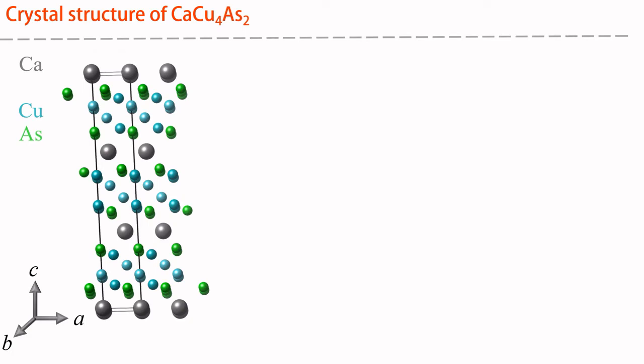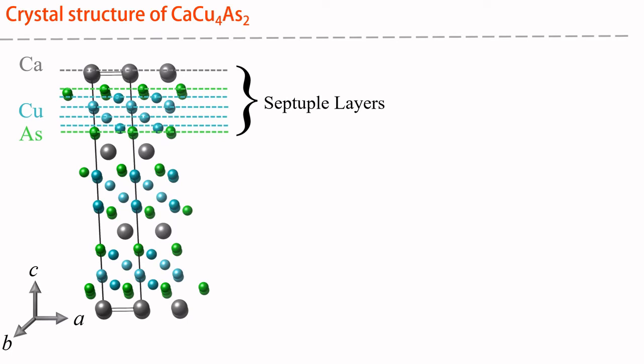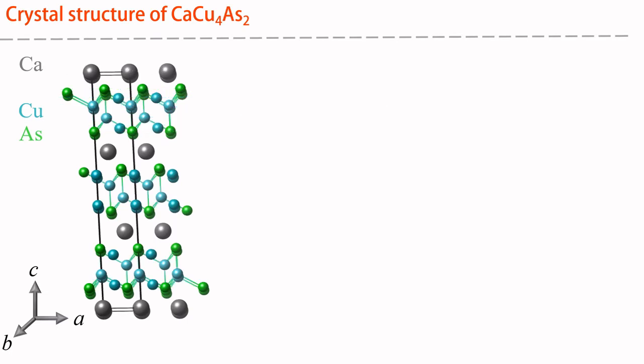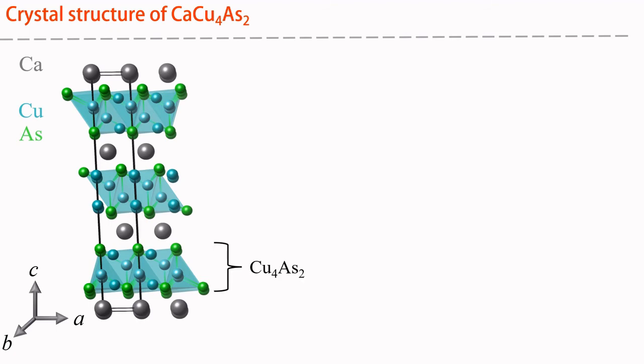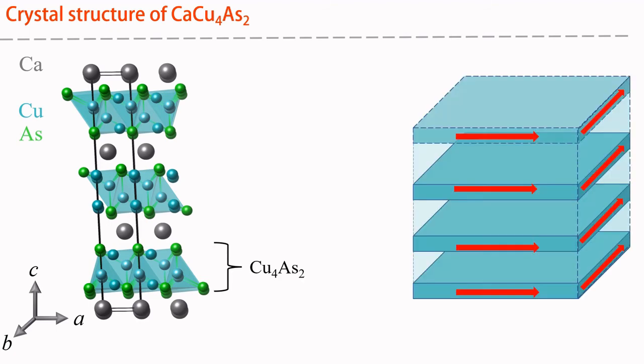Calcium copper four arsenic two has layered rhombohedral structure. Seven layers of calcium, copper and arsenic form septuple layers, and each unit cell has three such septuple layers. If we look carefully, copper atoms are surrounded by four arsenic atoms, constructing complex tetrahedral copper four arsenic two structure. This layered structure consists of parallel conduction channels, which has a significant effect on magnetotransport.